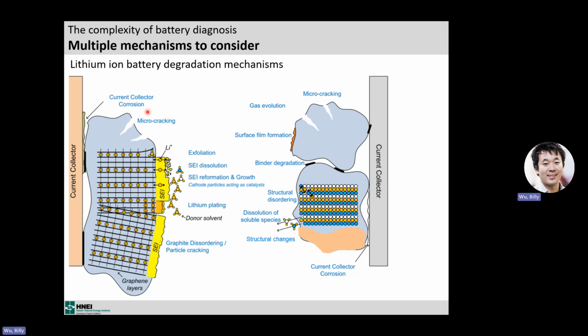And so that's why we're starting to think in terms of degradation, material science. I want to understand what happens. And sadly, when you look inside the battery, it's a mess. The battery does not work because the electrolyte is not stable and decomposes. The materials shift when they inflate and deflate. And that summarizes pretty much, I would say, most of the degradation that could happen in your cell.